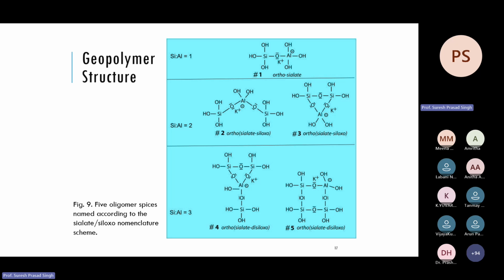So now this single unit of silica to aluminum ratio 1 is a structure like this one. But this H will not be there, OH will not be there. Finally, it will be oxygen. This hydrogen will be removed. So oxygen will be -2, but one charge will be shared by this silicon and one more silicon will be this, and the similar structure will be repeated to this side, this side, this side, this side. So it is a chain-like structure. So once the hydrogen is released here, it will again combine with the OH group, then the water will be formed. So I told you that during the process of oligomerization to polymerization, water is released. It does not need extra water as happens in the hydration of cement products.